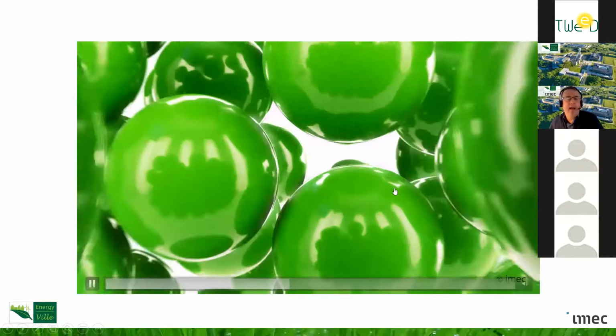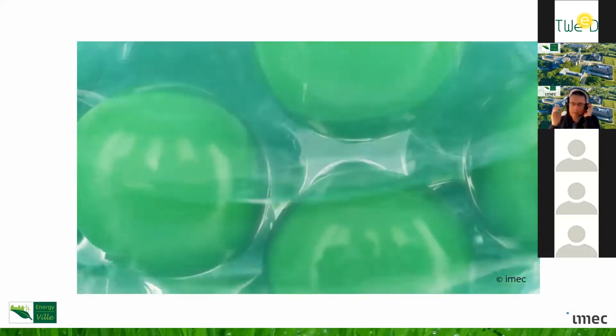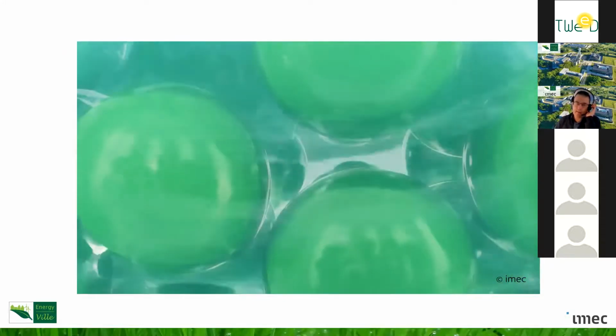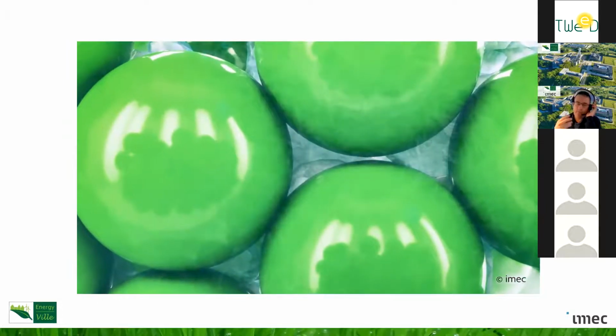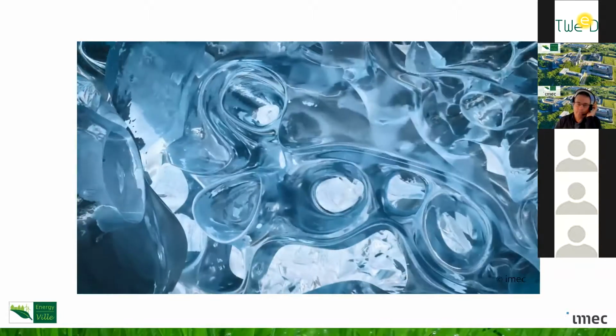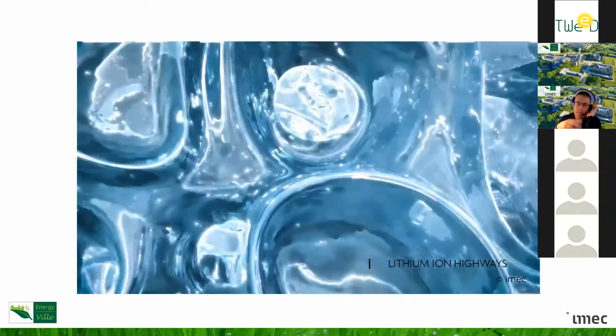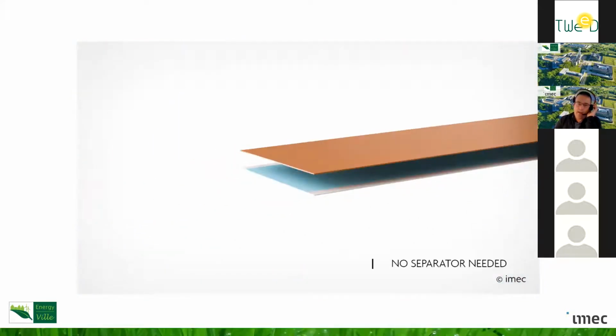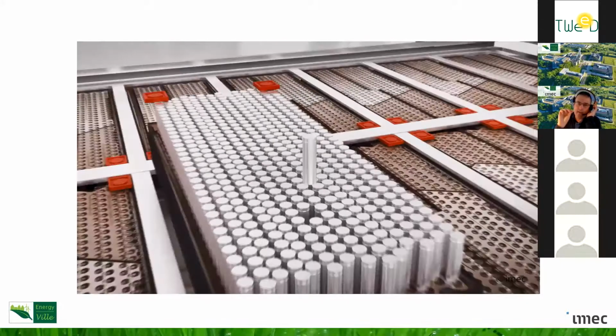Yeah, so we have the liquid precursor that is coating the films. And this makes it compatible with current battery manufacturing, because wet electrolytes are used there also, and we use it here also. We impregnate the film with this wet electrolyte, and then it solidifies. And by the solidification, you make an intense contact between the different particles, allowing you to have this very dense and intimate contact between the different materials. And so we have these pores, and these pores, while coated with this electrolyte, act as highways for ions, which go from the one electrode to the other. And we don't need a separator because there's a little bit extra of this solid material which forms the barrier between the different materials, the separator itself.